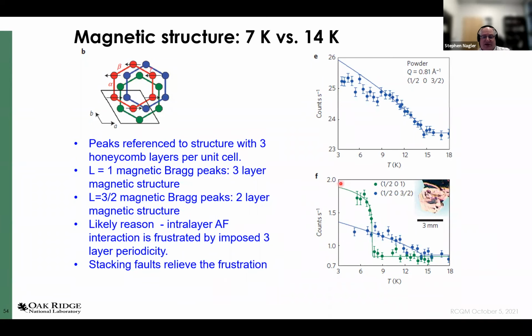So basically, the green one, the 7 Kelvin transition, is zigzag with a 3-layer periodicity. The 14 Kelvin transition is zigzag with a 2-layer periodicity. So what's the reason for this? Well, at the lowest temperatures, the crystals have at least a pseudo 3-layer crystal periodicity that imposes a boundary condition. It turns out that this material wants to have layers that are antiferromagnetically coupled to each other, but if there's a periodicity of 3, that's frustrated. So that lowers the transition temperature a bit. If I put in some defects by sliding some layers around, that relieves the antiferromagnetic frustration going perpendicular to the layer, and I get a higher transition temperature, but a broader transition.